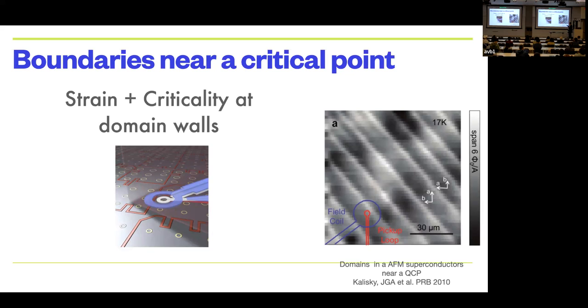But what they saw, but she's not measuring structural anisotropy here. She's not measuring anything structural at all. What she's measuring is the superfluid density, right? And what they found is that the superfluid density, in other words, the superconductivity, was much, much higher at the domain wall boundaries than it was anywhere else. So where the system had these defects in the crystal, where two domains met together and had the structural disorder, that is where the superconductivity was the largest.